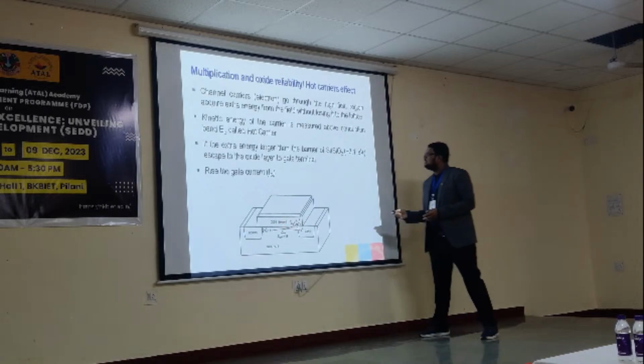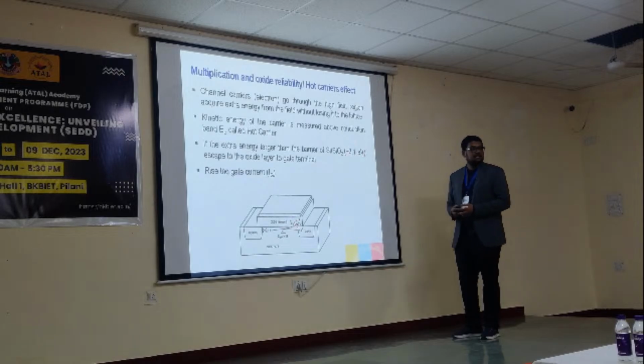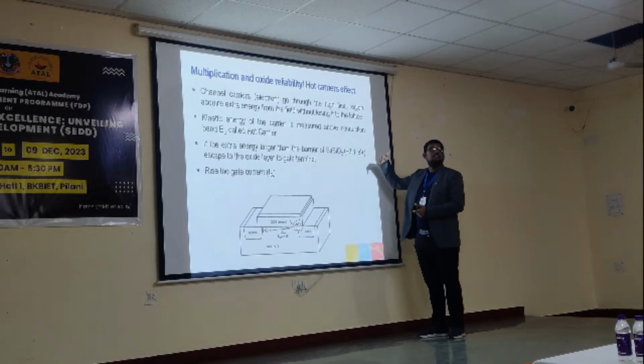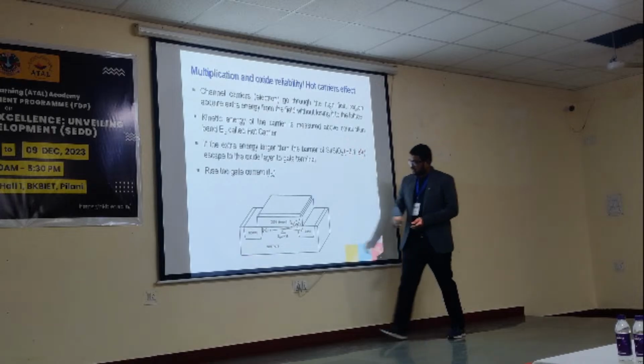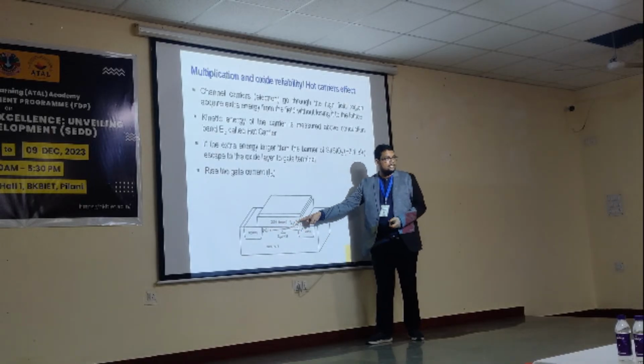The barrier is normally called the offset. This offset is around 3.1 electron volt. That is one of the important advantages of the silicon dioxide system. This offset is very high. It is the difference between the conduction band of silicon and the conduction band of silicon dioxide, around 3.1 electron volt. That's why, when electrons flow along the surface, they do not easily enter the oxide because of this 3.1 electron volt offset.